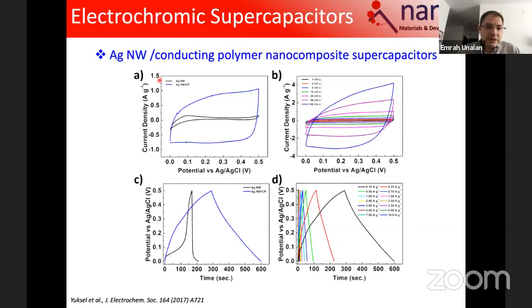So these are typical cyclic voltammograms. Don't want to get into too much detail, but the more square or rectangular it is, the better the capacitor, or the smaller it is, it is like a resistor, and it doesn't really have a storage capability. So as you see, once we put the polymer, it gets more and more rectangle-like. For sure, there is some storage for the silver. I believe it's due to the oxidation. There are 2 oxides of silver, as you know. One is reversible, but the other one is irreversible. So that is the Ag2O. So it can oxidize, but the current is very limited. So the storage is very limited as well. But our polymer completely, drastically changes the storage capacity.